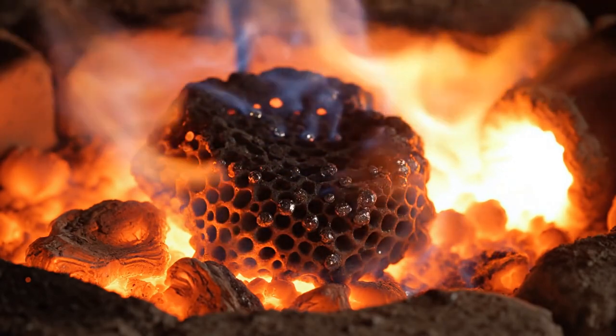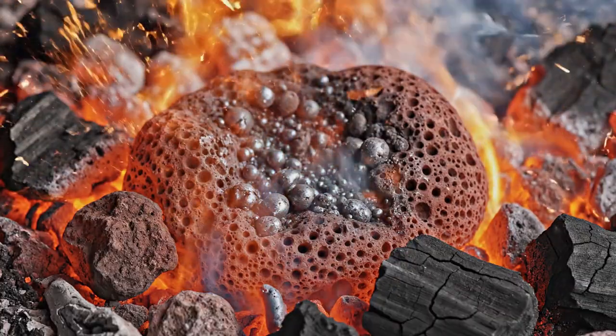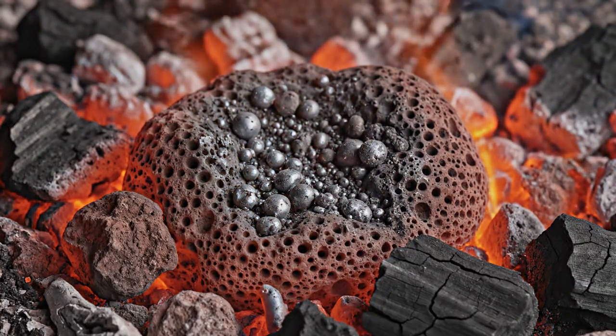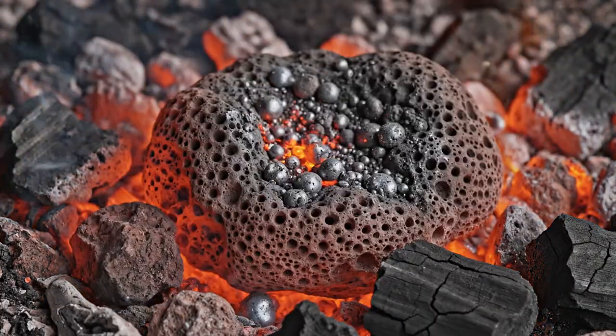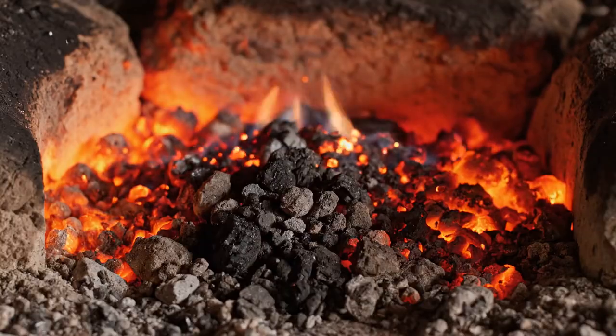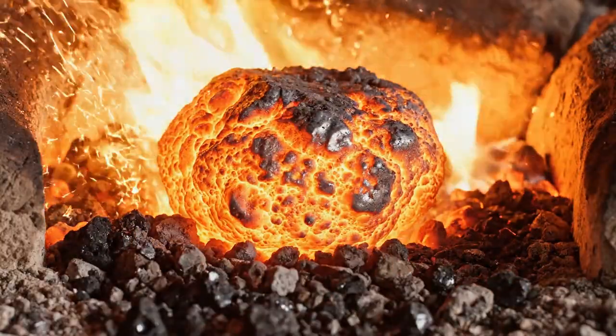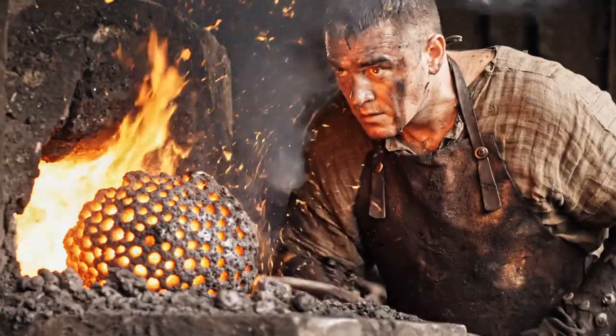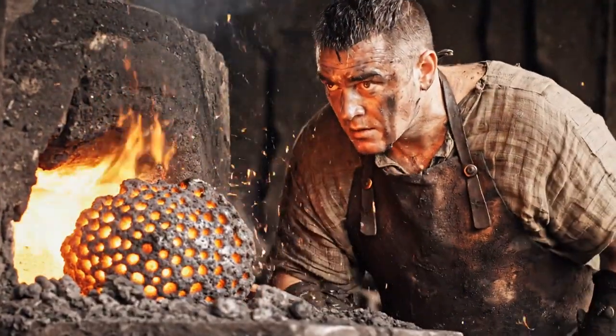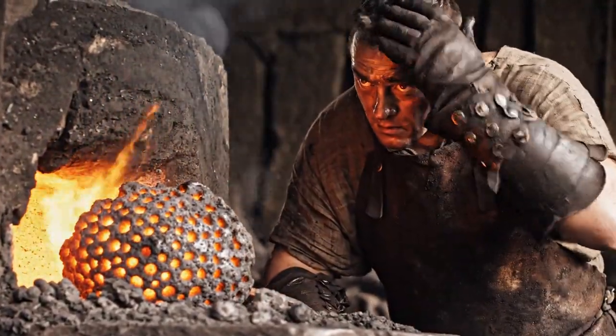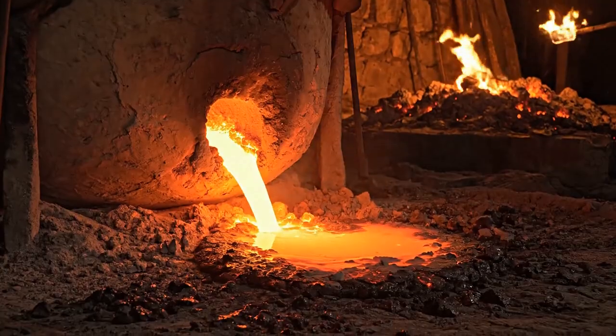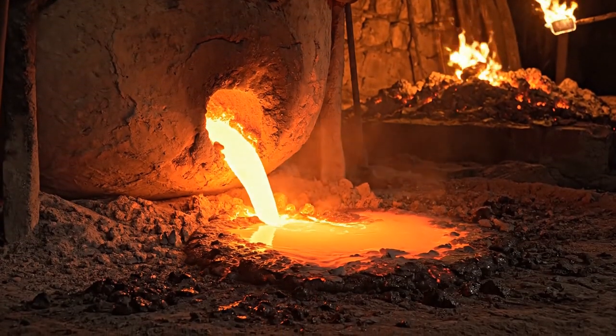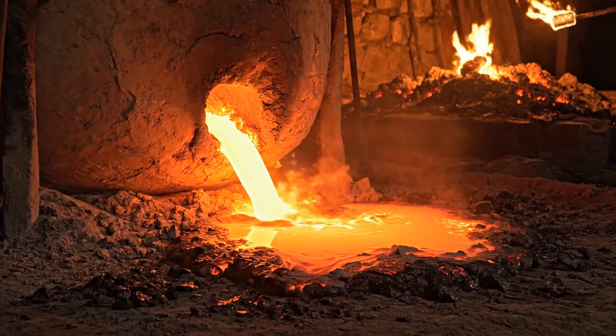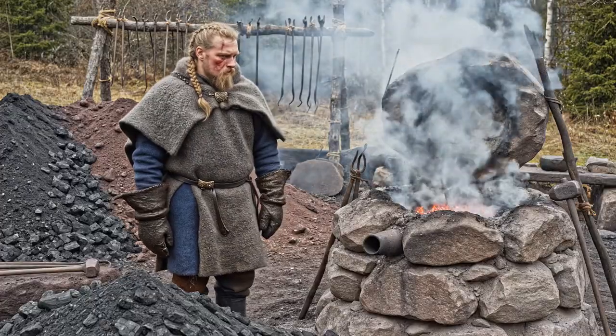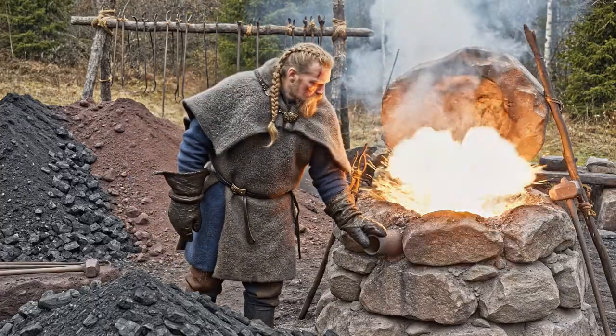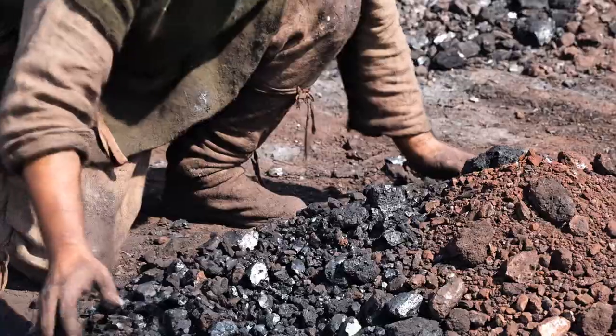Instead, at the lower temperatures of the bloomery furnaces, the iron oxide in the ore was chemically reduced by the carbon monoxide coming from the burning charcoal. The oxygen was removed, leaving behind solid particles of metallic iron that welded to each other, forming a spongy, porous mass called a bloom. Meanwhile, the unwanted material, silica, alumina, various impurities, melted into liquid slag that flowed down and out of the furnace. The yield was modest.